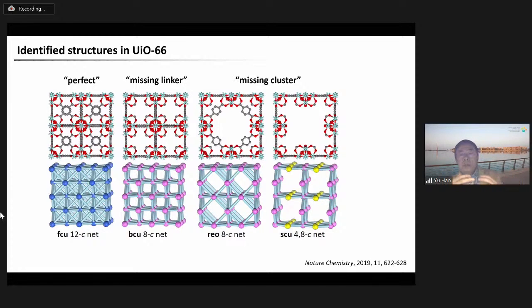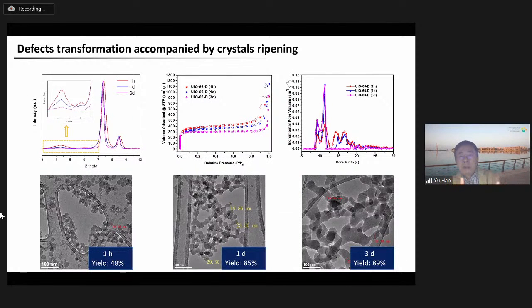And another interesting phenomenon we observe in this system is that the defects evolve with crystallization. The sample collected after 1 hour of crystallization, this one, consists of very small crystals, and it contains a large number of missing cluster defects. As the crystallization time is extended to 1 day and then to 3 days, the missing cluster defects become less and less, while the missing linker defects remain.